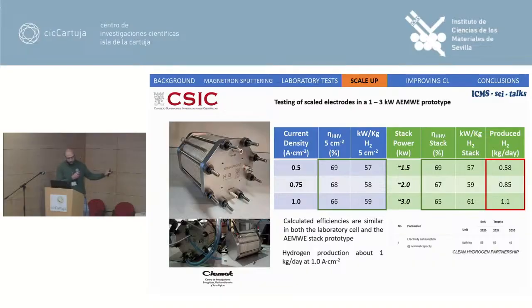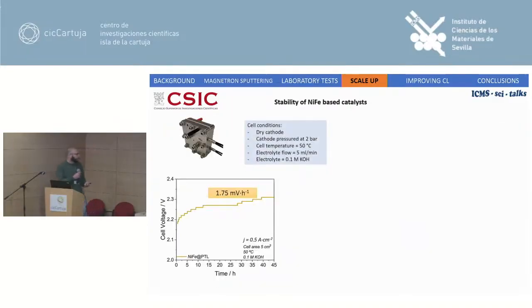So all these data are regarding the electrocatalytic performance, but what about the stability of this kind of catalytic coatings? We performed a 45-hour continuous working methodology by a chronopotentiometric method, and we can see that in our laboratory the degradation rate of our catalytic coatings is around 1.75 millivolts per hour, which is pretty good compared with the literature.